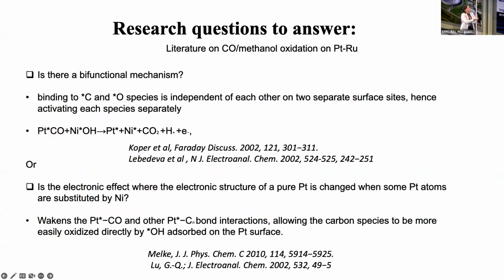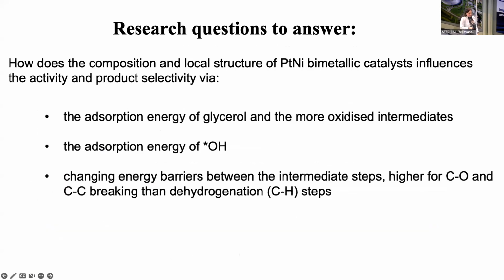And so the questions we wanted to answer, kind of inspired by the CO methanol oxidation and this bimetallic platinum ruthenium, was, will this be a bifunctional mechanism where in fact you could separately adsorb the CO on one metallic side and the OH on the other metallic side? Or is it the electronic structure of platinum that is modified by this nickel, and then you change the adsorption of these intermediates? And how does this work for glycerol? And so basically for glycerol, we wanted to understand how the adsorption energy of the glycerol and the oxidized intermediate is changing depending on the surface, the adsorption energy of the OH intermediate, and how the energy barriers between the different intermediates have changed. And clearly, this energy will be higher for CO and CC breaking than for the dehydrogenation steps.